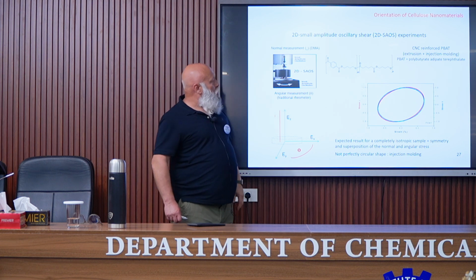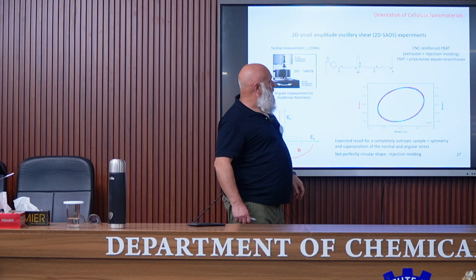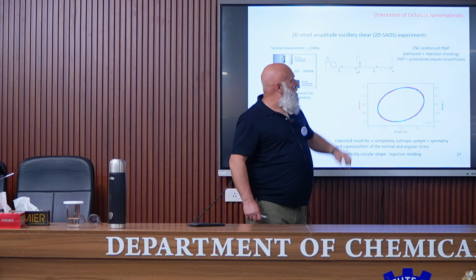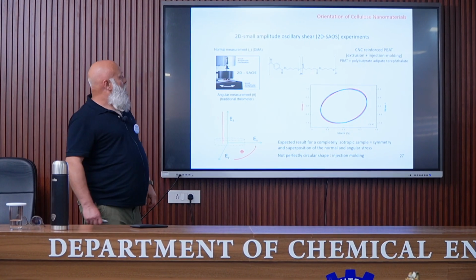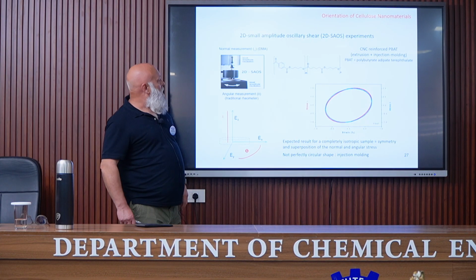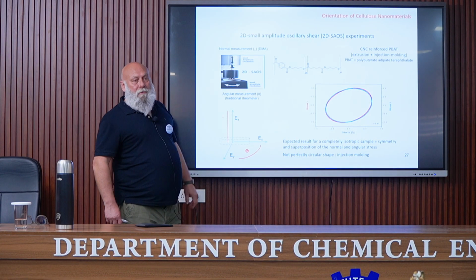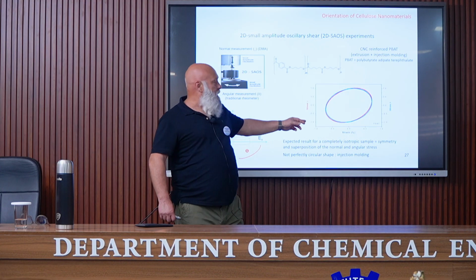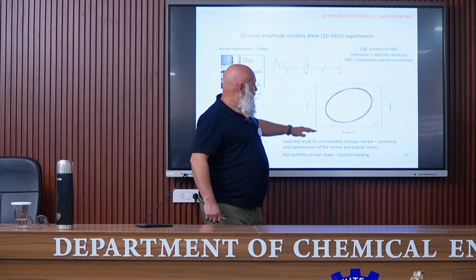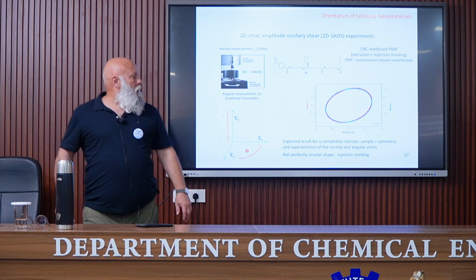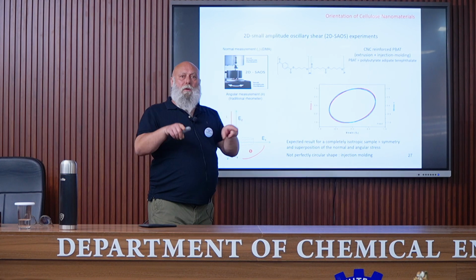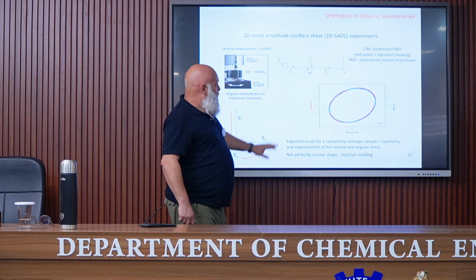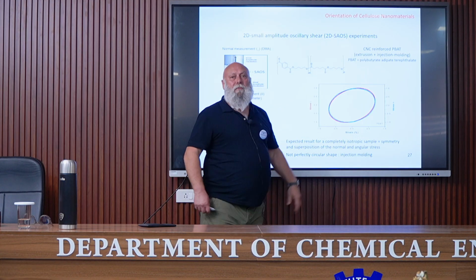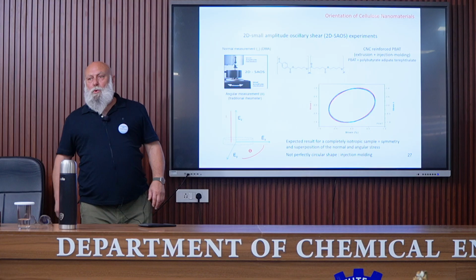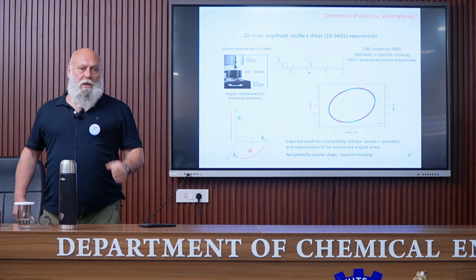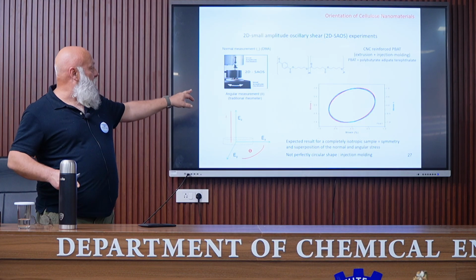For this experiment, we used nanocrystals, and for the matrix, it was PBAT, polybutylene adipate terephthalate. So it's this polymer, it's a biodegradable copolymer. What we obtain from this experiment is the evolution of the perpendicular stress and the angular stress as a function of the strain. What we should obtain is 2 circles, if there is no orientation. But we can see in this case that it's not a perfect circle. The reason is that during extrusion, and then injection, we have some orientation of the macromolecules. This is for the pure matrix.